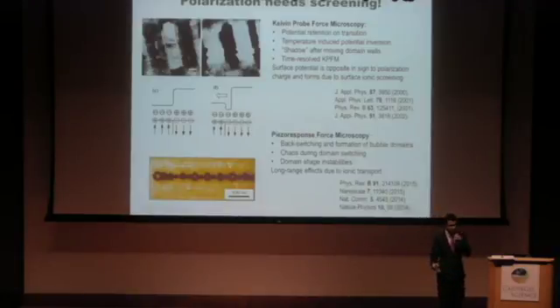In the absence of that, the surface is going to somehow reconstruct, because the bulk obviously wants to stay ferroelectric. If the bulk is quite large, the energies are going to be quite large, and the surface really has to follow the bulk. Over the last 2 decades or so, we've had a number of experiments, from Kelvin probe force microscopy, to try to understand surface charge dynamics in ferroelectric thin films and ferroelectric single crystals.